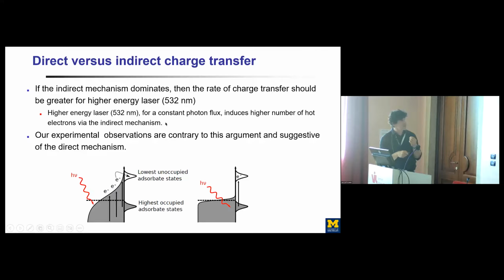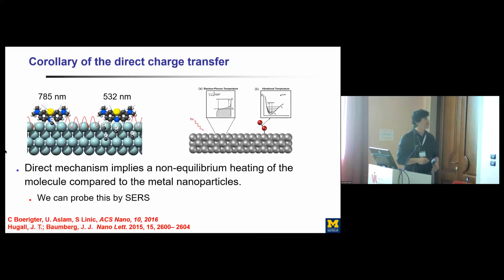So these experimental observations are contrary to the argument consistent with this direct charge transfer mechanism, and would point us in this direction of the direct charge transfer mechanism, where you have some resonant process that's driving the excitation at the interface between methylene blue and silver, causing excitations through that methylene blue and therefore heating of methylene blue under these 785 lasers. Now a corollary for this is that it could imply a non-equilibrium heating of the molecule compared to the metal nanoparticle. So what this means is that if I'm moving electrons selectively through this molecule, I can have intensities of light where this molecule gets hot and the nanoparticle itself is not hot.